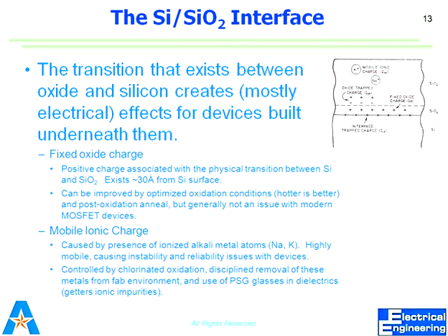This is the part where the diffusion process comes into play, because oxygen comes from here and needs to diffuse through the oxide. At this point it will react and the oxide thickness will increase. So after diffusing through here, the chemical reaction comes into play. There is always an interface between silicon and silicon dioxide. This point is called the silicon-silicon dioxide interface.